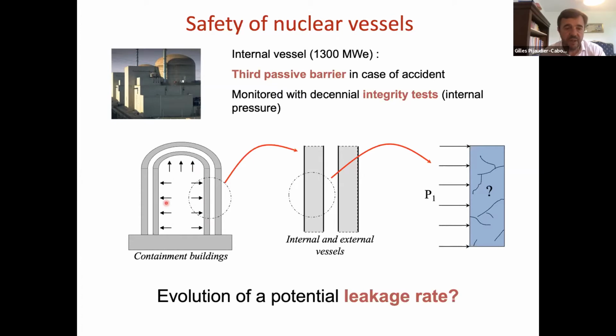Basically, what they do is apply a pressure inside the vessel - of course they stop everything first. They apply a pressure and measure the leakage rate, and if the leakage rate is above a certain threshold, the facility cannot be restarted. So the issue is to evaluate a potential leakage, which is due to the aging of the concrete.